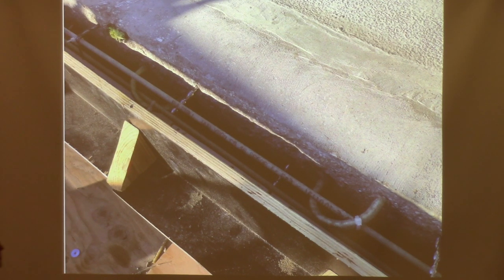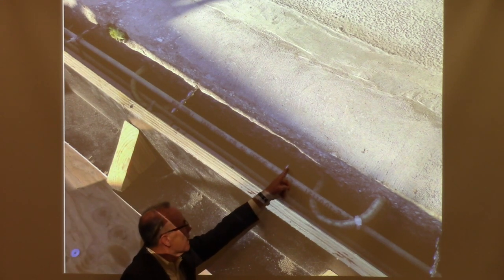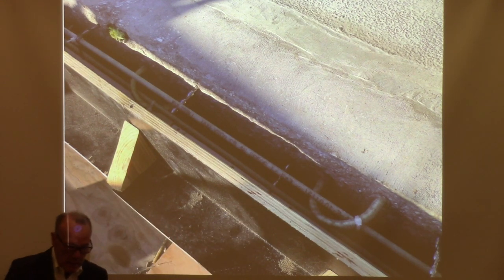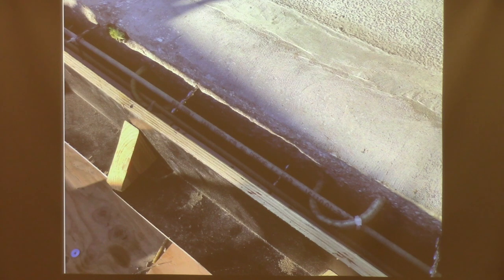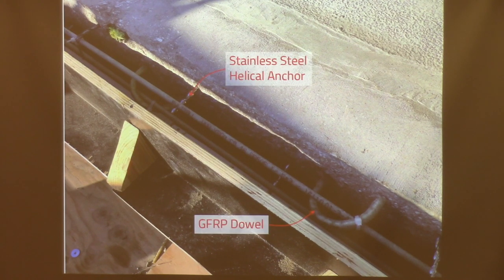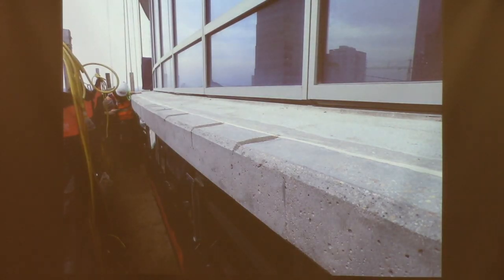And then we also use some, you see these little items in here. Sometimes the PT was so close together that it was very difficult to get a GFRP dowel in there. We used stainless steel helical pins down in there as well. And of course, stainless steel is for the most part inert to that type of corrosion. So GFRP bar, stainless steel.